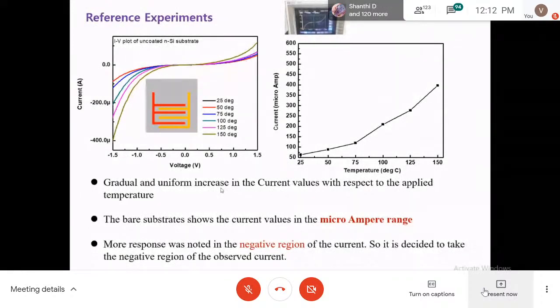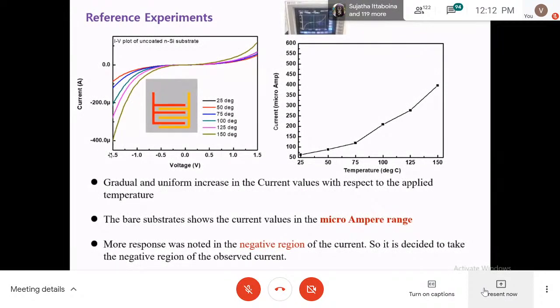The bare substrate shows current values in the microampere range. More response was noted in the negative region, because in the positive region there was not much electrical response. So we took only the negative region, where there is more response. The response means the sensing. We took the 1.5 voltage range as better to observe the readings. So the useful operating range would be from minus 1.5 to 1.5. When we convert this response into a graph, it will come like this.